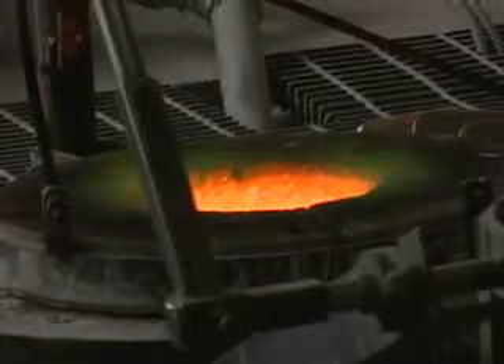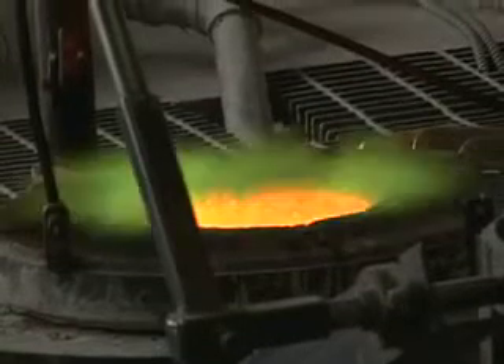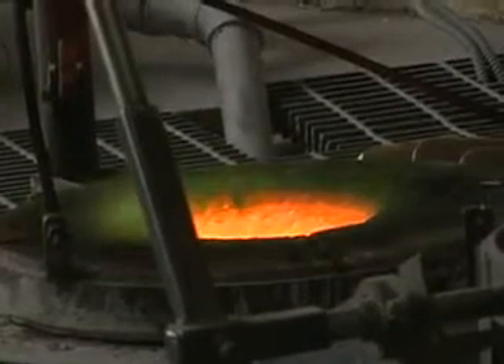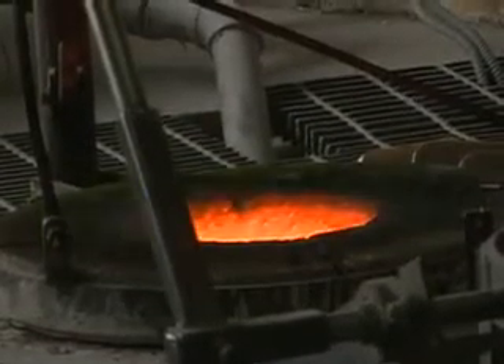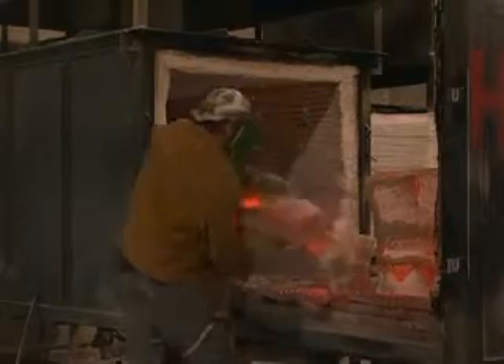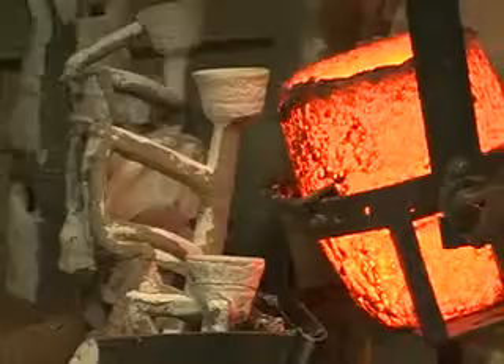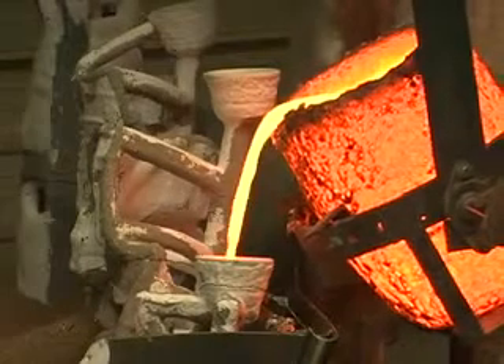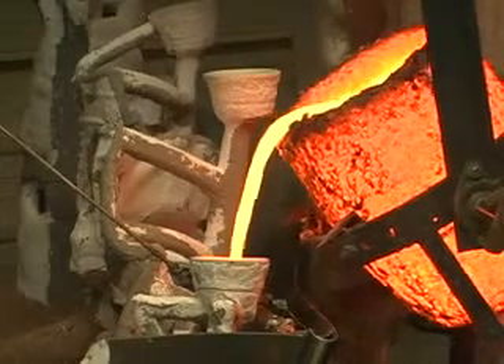A large crucible fired by a furnace is filled with bronze ingots and melted. The metal begins to melt at approximately 1700 degrees. The ceramic shells at this time are also heated in a kiln to approximately 1100 degrees to aid the flow of the bronze. When all temperatures are reached, the shells are removed from the kiln and the molten bronze is poured into the shells.